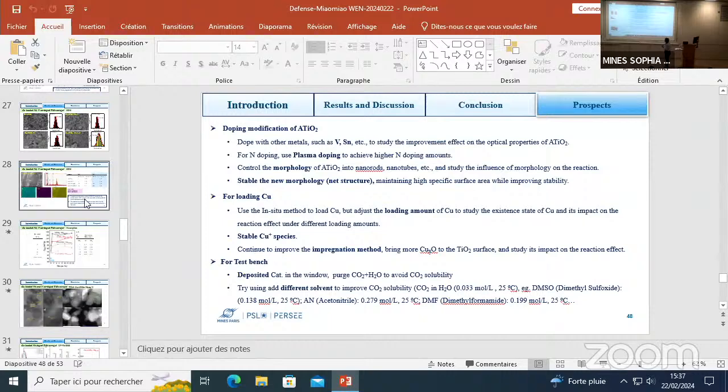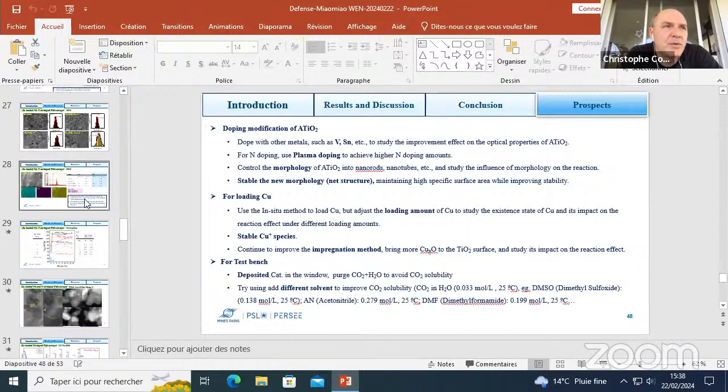If it's niobium 3, it's more reactive. I didn't talk about niobium 3; I mentioned chromium 3, for example, for another kind of doping. But you chose niobium 5. Yes, because it's quite easy to substitute, since the ionic radius is close to titanium.